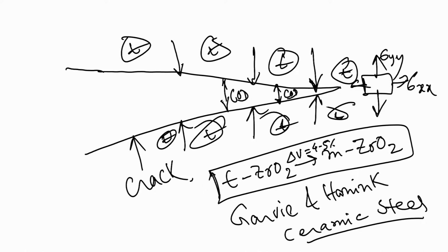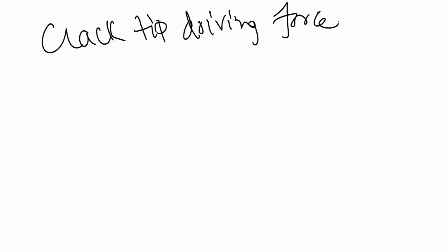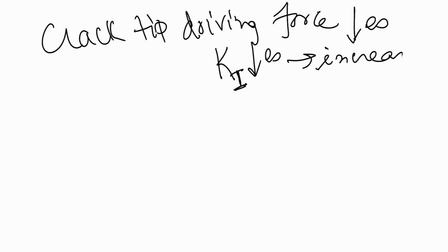So, if the driving force for the crack propagation is reduced, that leads to the increase in the fracture toughness. So, a couple of things that let me also tell you in another slide. So, these other things that I wanted to discuss, that if the driving force available at the crack tip decreases, that means stress intensity factor at the crack tip decreases. So, if this Ki decreases, that leads to increase in the fracture toughness or increase in crack growth resistance.